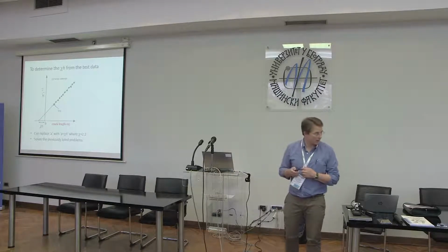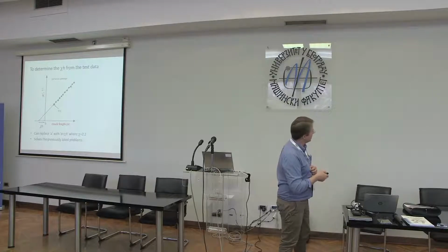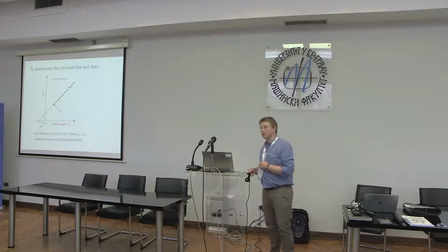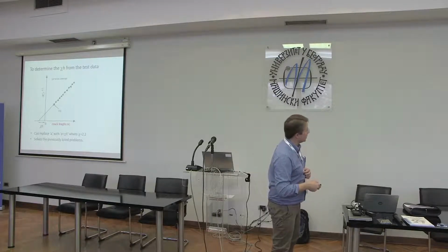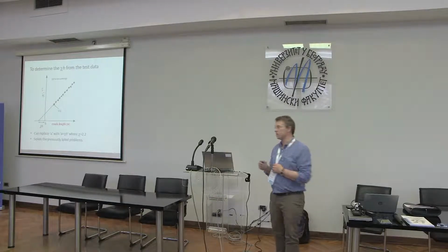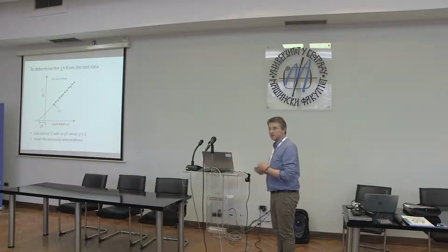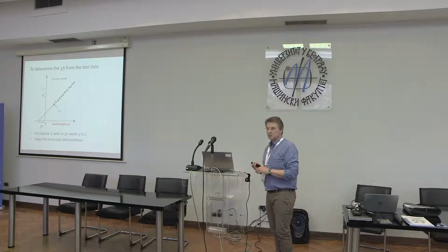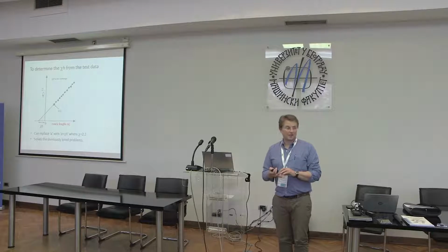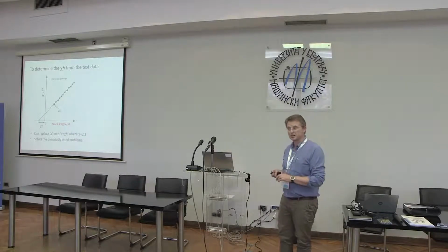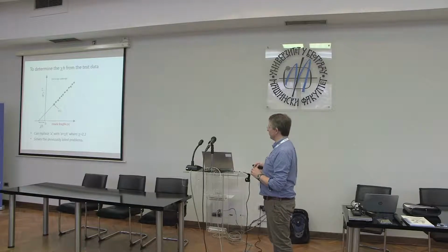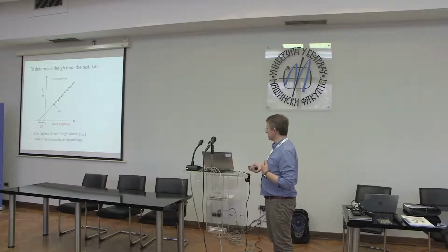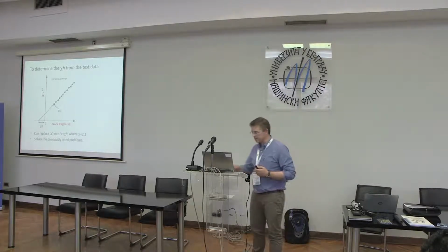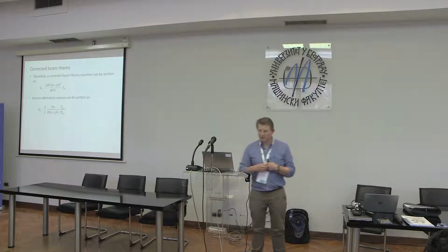Physically, this is what's happening in the experiment. You're looking at the compliance to the 1/3 against crack length. And of course, if simple beam theory was spot on, the data that you measure in the experiment would go through zero. And you can see that they don't. They go through an offset, and that offset is that correction term. So this was a nice fix for the experimental data. It was built into the standard for measuring G1C in composites, and it's been used very widely. And it solved many of those issues that we talked about.